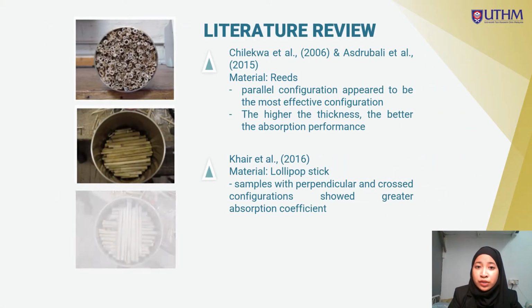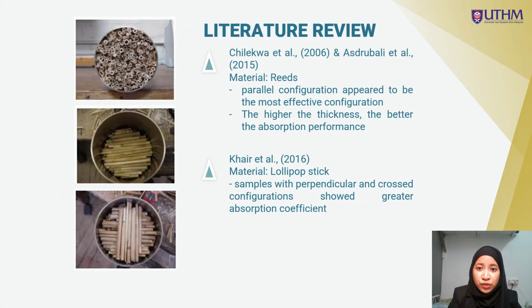There is not much research conducted to investigate the relationship between acoustic absorption and the configuration of hollow structures. In 2006, a study on utilizing hollow structures as acoustic absorbers arranged reeds in three configurations of parallel, perpendicular, and cross as shown, and concluded that the parallel configuration appeared to be the most effective. A deeper analysis was performed in 2015, where the reeds were fabricated into different thicknesses with three different configurations as well.